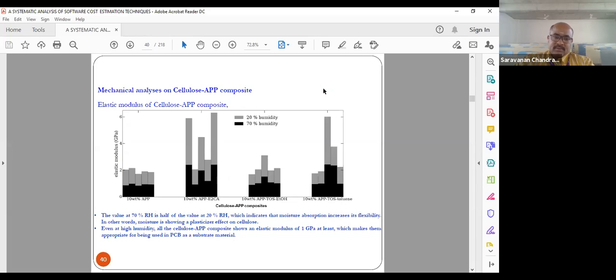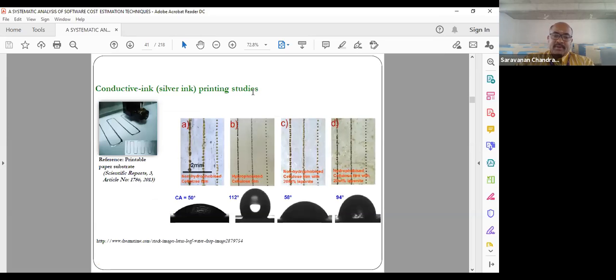Concerning the mechanical studies, we measured the elastic modulus, which defines the stiffness of the material. We observed it at two different relative humidities, because across the world, at the market level, different regions have different relative humidities. So those are the two extreme relative humidities we used, 20% and 70%. The dark one is the 70% and the light color is the 20% relative humidity. The dark one is more flexible when you compare with the lighter one. It means that humidity is acting as a plasticizer.